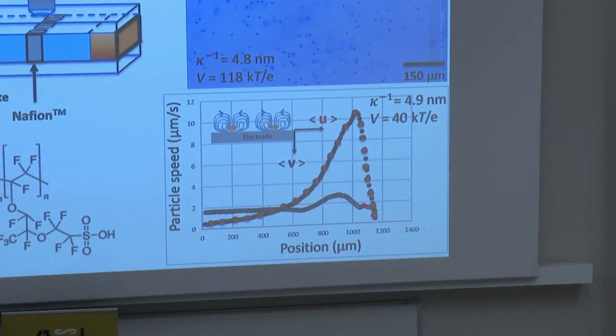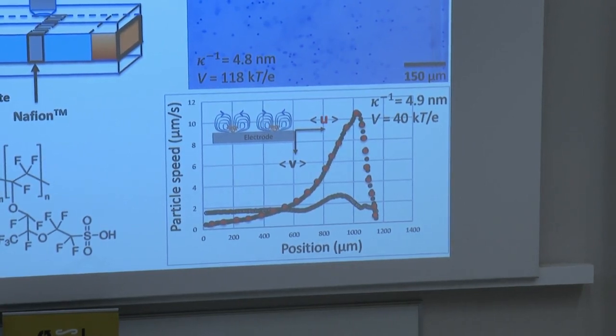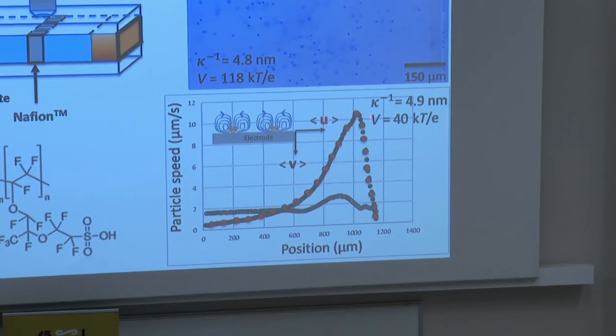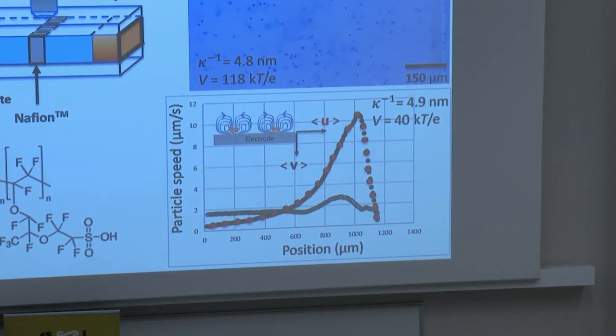Roughly at about 1200 or 1180 microns. It initially rises with distance, meaning this fluid is moving faster as you're going away from the wall, but then it starts to fall. And this point is what's called a boundary layer. So there's a transition in the physics that are occurring as you go from the wall outwards, such that if you were far away from the wall, you might think that the fluid is actually slipping at this plane. Okay, so this is a kind of interesting result.